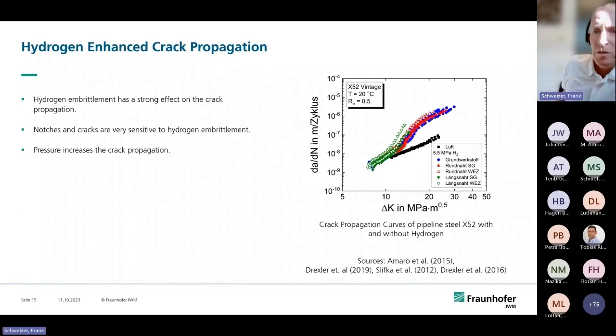Then what we also did and do: if you have hydrogen in your system and you have small micro cracks, the crack propagation will be different in hydrogen than in inert gas, for example. So we really see a strong effect on the crack propagation. This is what you see on the right side. I'm sorry, this is in German. I only have this diagram in German. So what you see here, you have dA, dN.